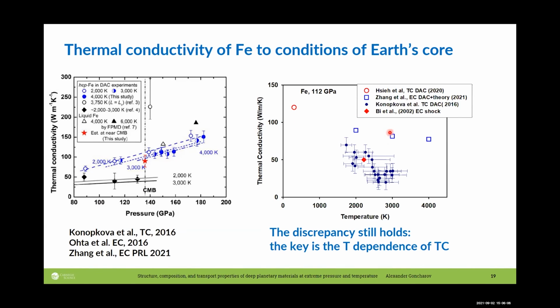So this is the result of essentially Zhang et al., where they show quite moderate change of thermal conductivity with temperature. And our results, I mean, results of Konopkova and others, show much stronger change, but we cannot extrapolate that to zero temperature, to 300 K temperature, because the accuracy of these results is not very high. So it is important to perform that kind of experiments, which we do, at lower temperature.